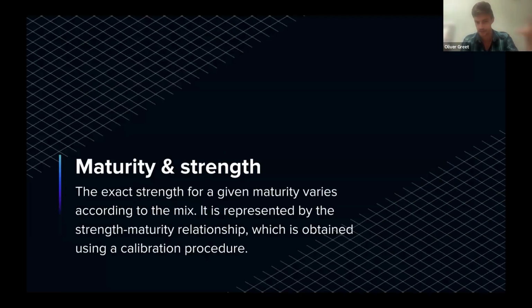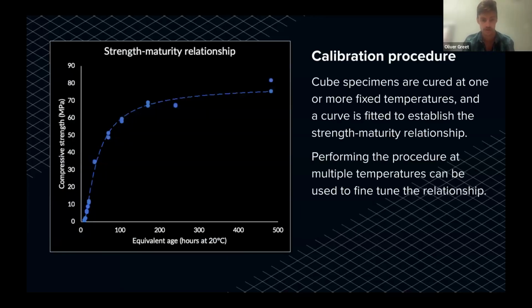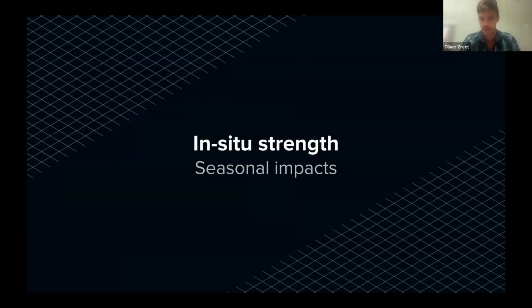So using this information, i.e. the rate of reaction, we need to couple that with some other information in order to obtain the in situ strength, which is really what most of our users are concerned with. They want to understand how strong their concrete is within the structure itself. So in order to do that, there is a calibration process. Essentially, the relationship between the maturity and the strength is going to be distinct for every different mix. And so this can be determined by casting some samples and curing those in standard conditions. And you get a curve, as you can see here, and this, coupled with the information I just ran through, can be used to develop predictions of the in situ strength condition itself.